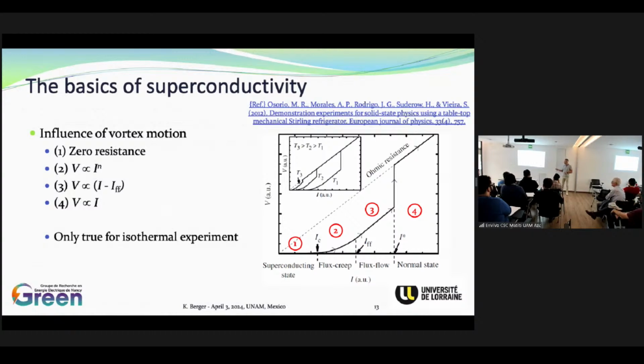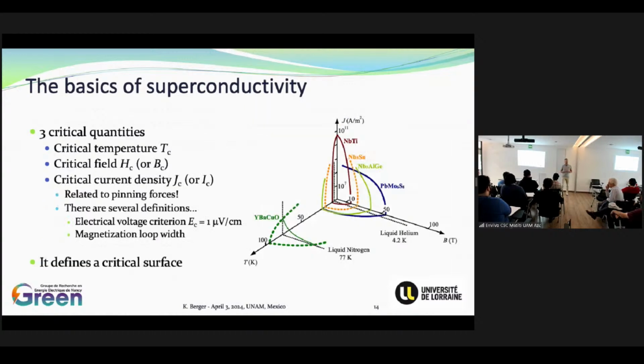So here, what you should know is that there are some definitions of critical currents, which make the superconductor not dissipating, or dissipating, but still superconducting in this area. So different kinds of definition. All this together means that you have three critical quantities: the temperature, the critical field, and the critical current density. All these quantities are related to each other, so they are connected. In fact, they define a surface between the three axes. Above this surface, the superconductor is not superconducting or is dissipating. And below this surface, the superconductor is in the superconducting state.